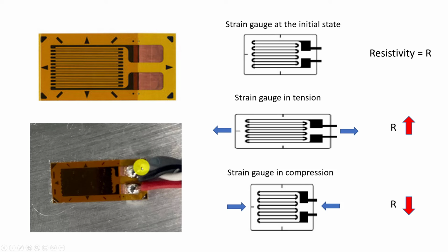We also limit the length of the wire that is stripped off to a 1/16 of an inch right here from the insulation. We also want to see the insulation not making contact with the base metal underneath. So this is a pretty clean install. We don't have any solder or connection of current from one pad to the next. Now some of you are going to say, this has two pads.